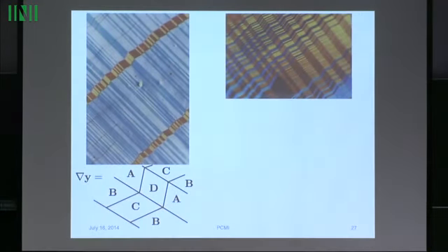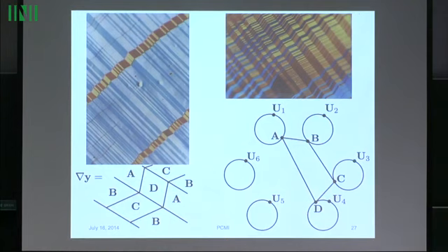Okay, so for example, we could do this example. This is that material that I just described, that copper, aluminum, nickel alloy. And it turns out, so you do this calculation. I'm doing a calculation again, which would take 2 or 3 slides if I wrote it all out. But here, you take any matrix on this well. So A is a rotation matrix times U1. And it turns out that this well is compatible with this well. Now, the way I wrote the lemma, this matrix A would have to be the identity, but it's easy to change it by post multiplication to any A.